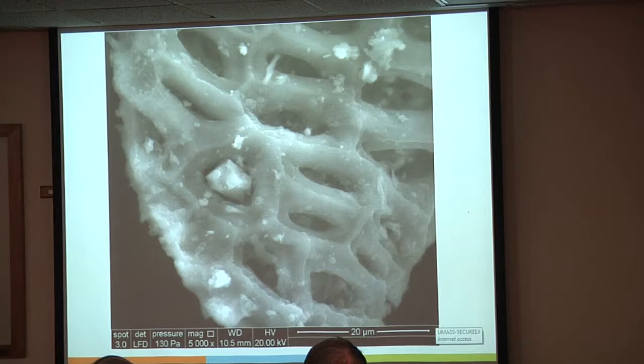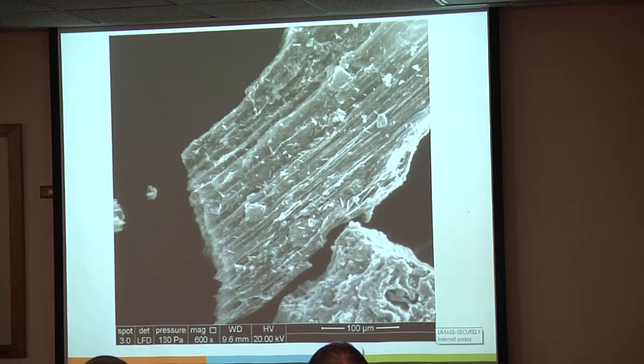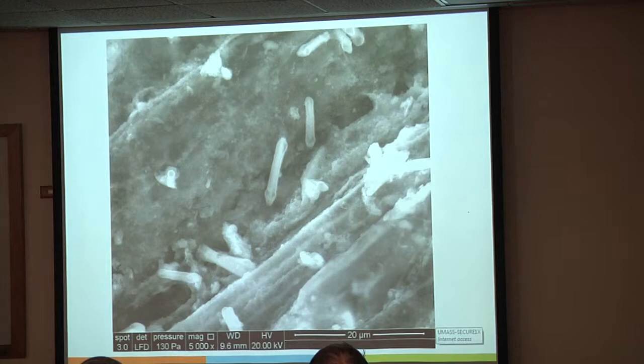This is the material treated at pH 12. What's interesting is you can start to see all of these little lines popping up, and if we zoom in, there are very regular shapes. This is the calcium deposition on the surface, which is most probably what's responsible for the phosphate absorption. I have a couple of samples I haven't tested yet that have actually been loaded with phosphate, so we'll see how those compare.